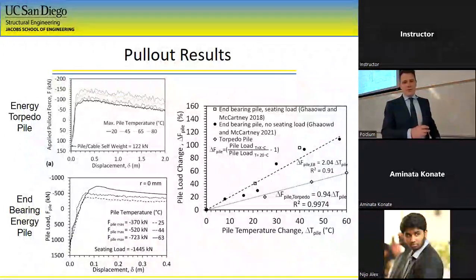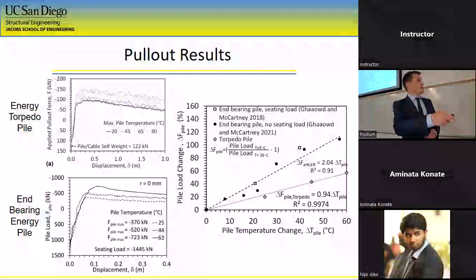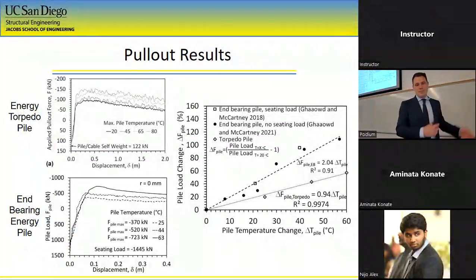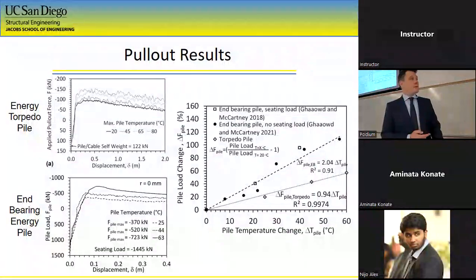So I have a lot of other experimental data that I could show you here, but these are just the final results showing that as you increase the temperature, the pullout capacity increases. And in fact, the pullout capacity can be as much as 100% if you heat the pile up to 60 Celsius. So I think this is a good potential area where we can use heat to improve the capacity of our piles.